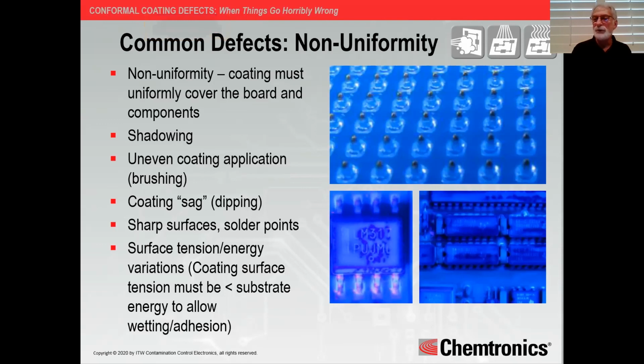There's also coating sag, and you'll see this in dipping. Now, I do have to point out that this is specifically addressed in A610. It is allowed. But as the coating settles from a dipping process, it accumulates at the lowest point. Could it be a defect? Possibly. But it is allowed as long as it does not affect the form, fit, or function of that component or that part in its service environment, the end-use environment, then it's not considered a defect, at least according to A610. Your criteria may be different.